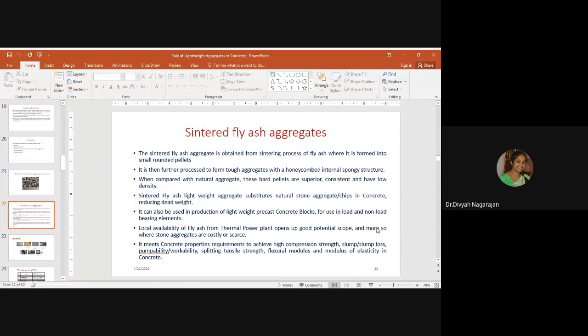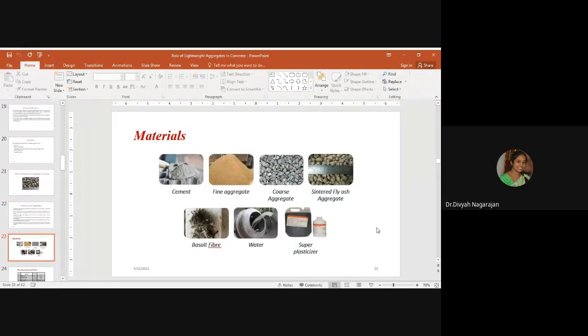The local availability of fly ash from thermal power plants opens up good potential scope, and more, since stone aggregates are costly and also scarce. It meets concrete property requirements to achieve high compressive strength, slump, workability, split tensile strength, flexural modulus, and modulus of elasticity of the concrete. The materials used for the present investigation were cement, locally available fine aggregate, coarse aggregate, crushed bluestone aggregates, the sintered fly ash aggregates, and basalt fiber.